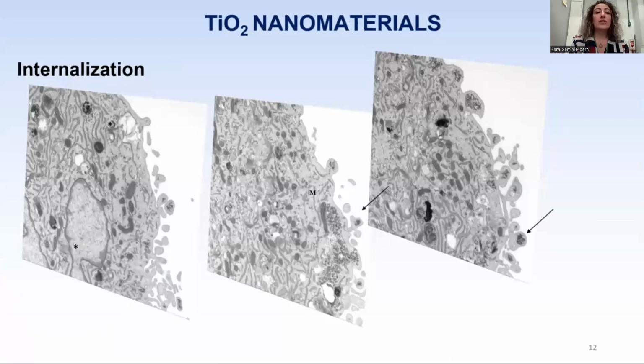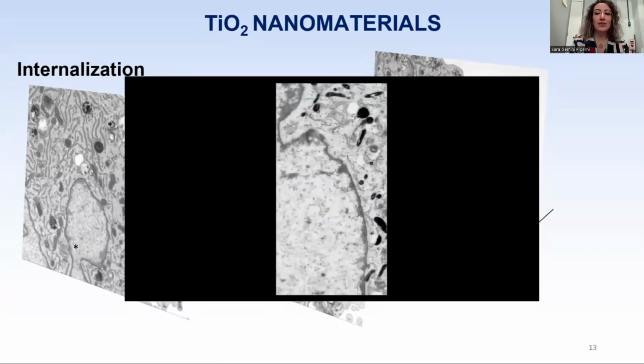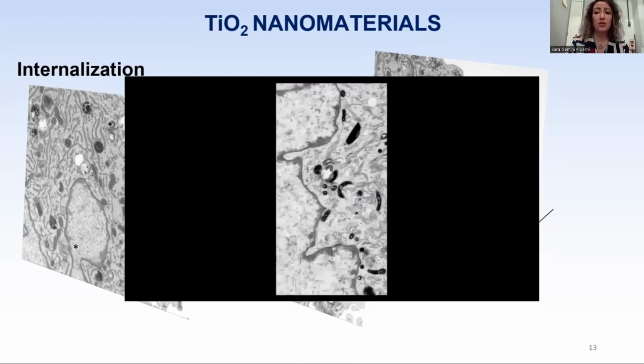So after our dispersion protocol, we first evaluated the titanium dioxide nanoparticle, and we want to see the internalization in osteoblast culture using a focused ion beam microscope. This microscope is almost identical to a scanning electron microscope, but it uses a beam of ions rather than electrons to probe.